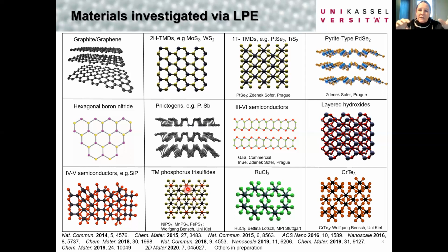The advantage here is also we don't need high quality crystals, big, beautiful single crystals. We chop them down anyway. So we can live with powders, and therefore it's easy for us to investigate materials that are not commercially available and provided by collaboration partners. Here you see some examples, and often these collaboration partners cannot make large single crystals, but more powdered materials with powdered texture. So here the liquid exfoliation process is an advantage over beautiful sheet isolation by micromechanical exfoliation, for example.